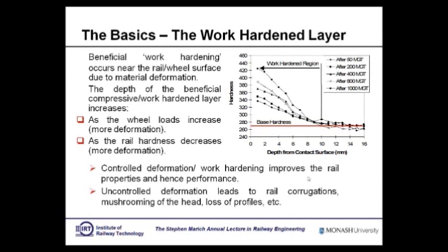I'm doing the extreme situation. So in a jokingly sort of fashion, Malcolm Kerr and I, who's the chief engineer at Railcorp, used to say that when you lay a track in a passenger system, low loads, so the material doesn't work harden too much, what you should do is actually bring over a heavy-duty iron ore train with 40-ton axle loads, run that over the system, the material will work harden, and then get the work train off again and run your passenger trains over it.